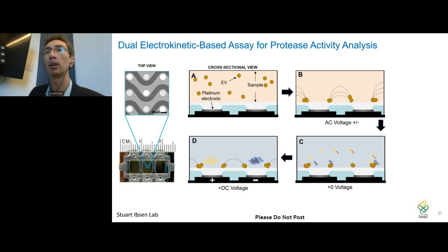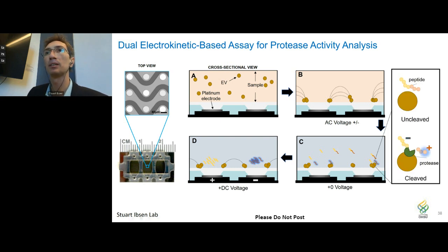We are looking now at protease activity on the exosomes themselves. And this is the very first time that any electrokinetic device has been used in a dual electrokinetic mode. So what we do is collect the exosomes as we do normally, as I've shown you before. But after they're collected and purified, we can then come in with a peptide that is specially designed to be cleaved by the protease that we're interested in. And when it's cleaved, that creates two charged fragments, one of which is positively charged and fluorescently labeled. So we can introduce this peptide to the collected particles, and then we can change the chip into an electrophoresis mode, not dielectrophoresis, and collect these positively charged fragments.